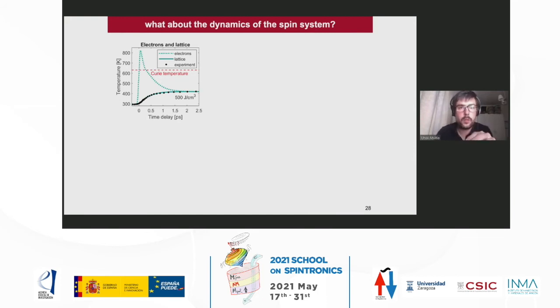So this is what we obtained. The experiment was about the lattice dynamics, and we can reproduce the lattice dynamics with a very simple two-temperature model, including the spin energy. We also obtain from the model the electron temperature, which goes above the Curie temperature.